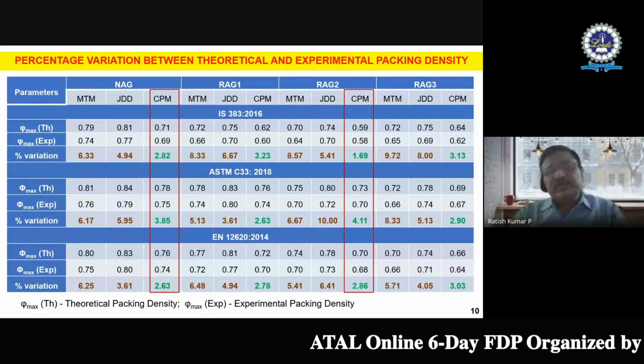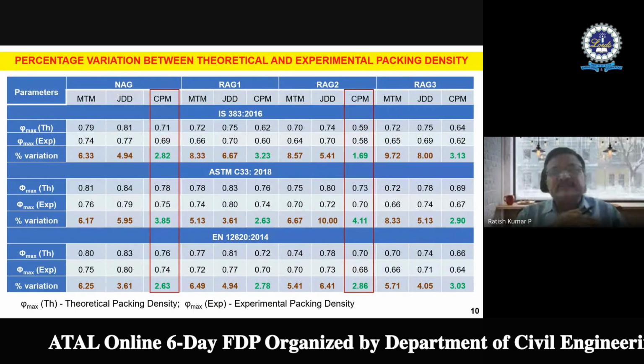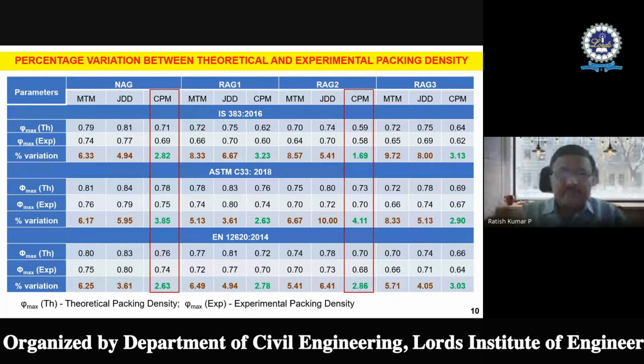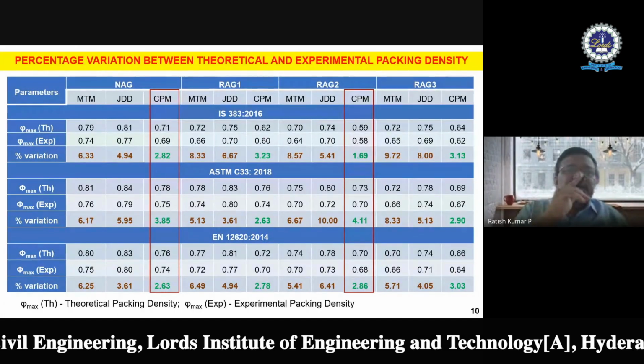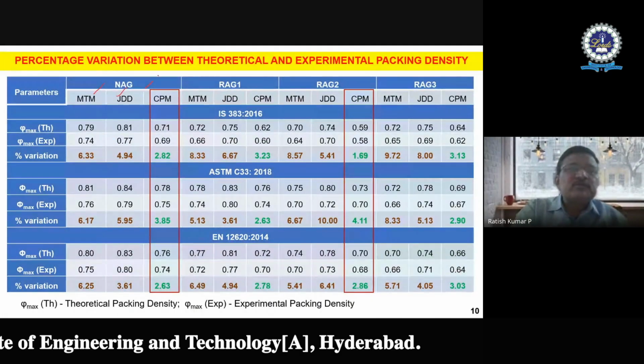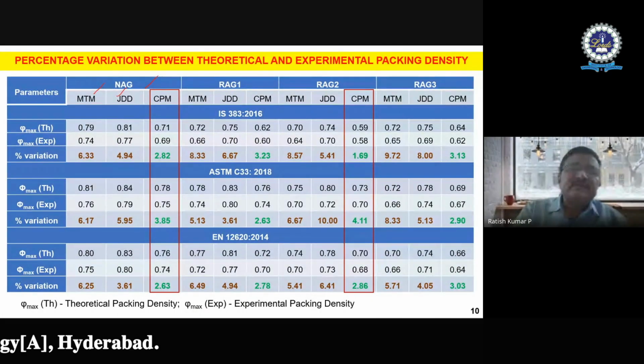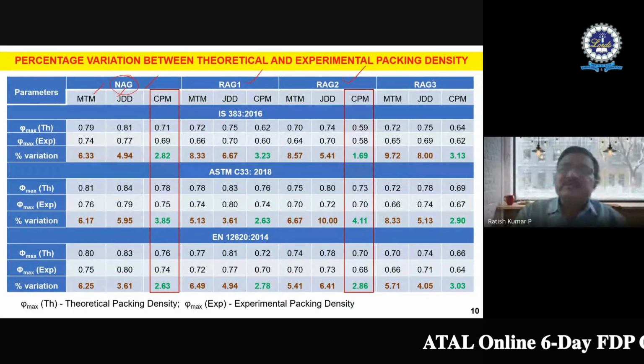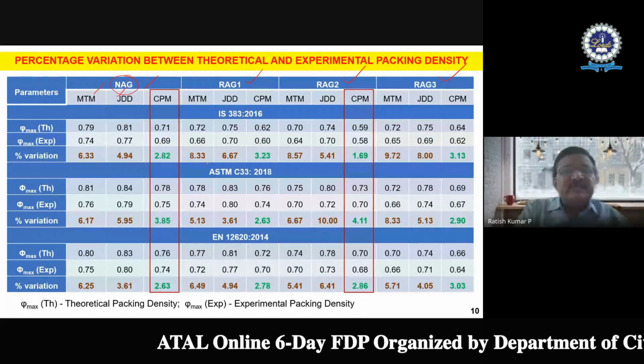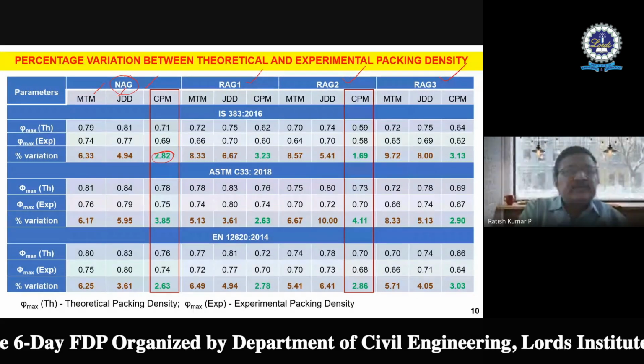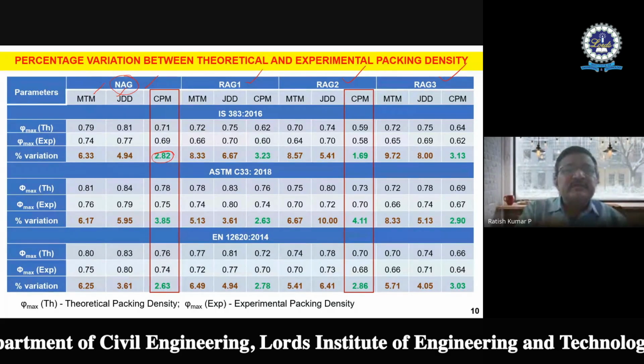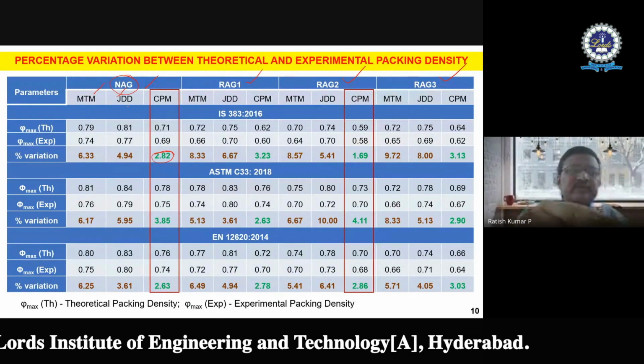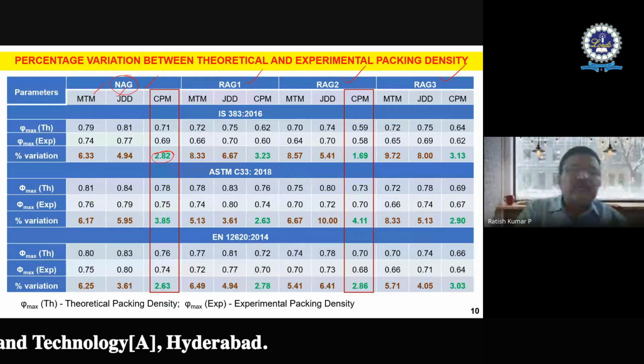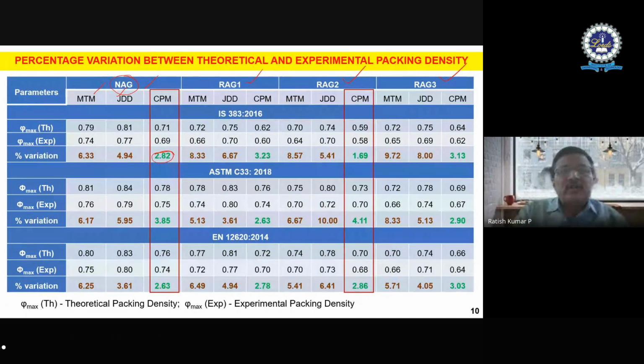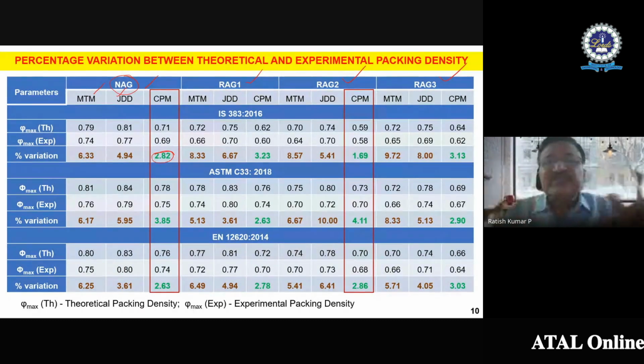Now here I'm just trying to show a table. I know you will not be very much interested in seeing the tables, but I also have to show some figures, some standard values basically. Now, there are different methods which I just proposed, and if I show you the CPM model, for example, the natural aggregate based concrete versus the first generation, the second generation, and the third generation, you can see that with a lesser percentage variation, I could get a good amount of density using the CPM method, though I'm also able to get it with the J.D. Dewar model and the modified Toufar model.